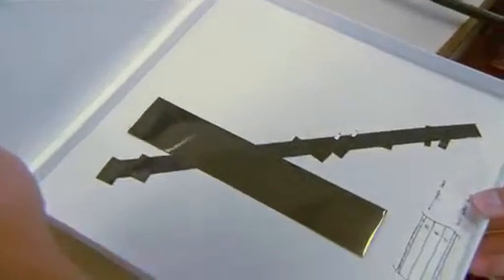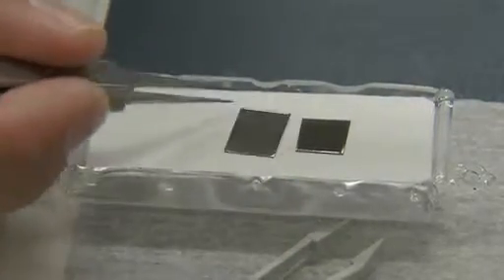You can imagine replacing the wire in many of these types of electromagnets. You still have to cool them, but not quite so much, and you achieve a huge benefit in the size of the magnet because you can put around 100 times more current through the same cross-section of a superconducting wire than you could through a copper wire.